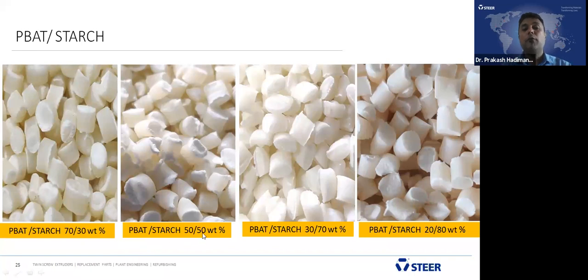And when it comes to 50-50, meaning starch 50% and 50% PBAT, here also, no color change. It retains the color, with better dispersion and miscibility of both the blend components. There is no black speck, no rough surface. And at 70% starch, no change. And at 80% starch, we observed a slight change in the color, but it was good.